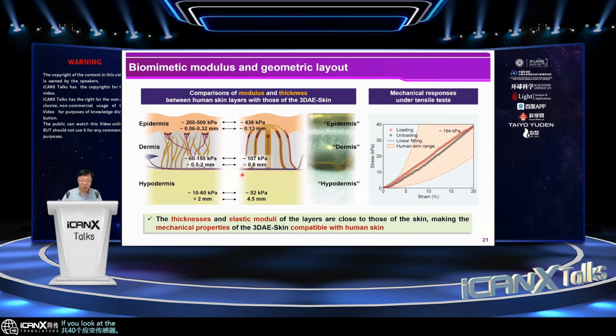If you look at the cross-sectional view of the 3D e-skin and the human skin, you can find that the thickness and elastic modulus of each layer compare well with each other for each of the layers, like the epidermis, dermis, and hypodermis. For example, the thickness of the epidermis layer in our e-skin is around 0.13 millimeter, which falls into the typical range of epidermis in human skin. And the elastic modulus also falls in the typical range of elastic modulus of the epidermis in human skin.